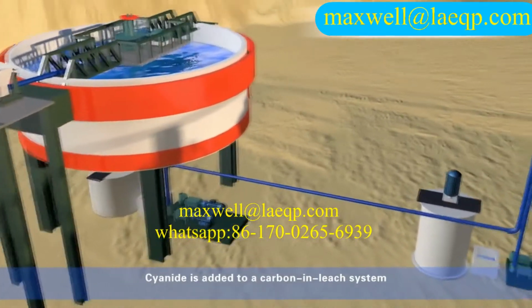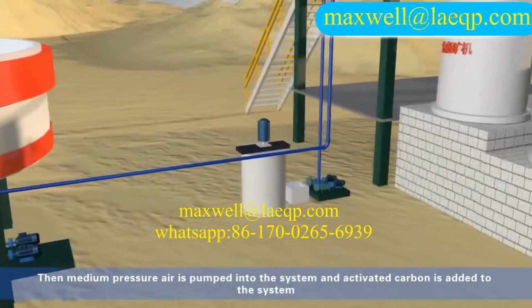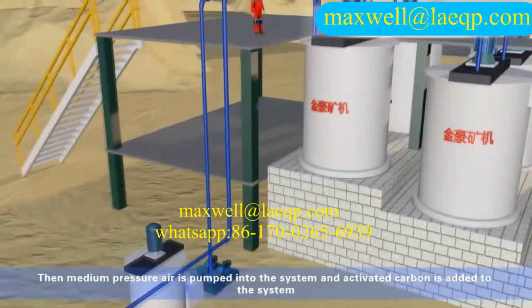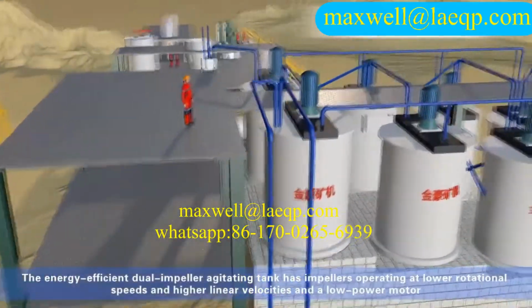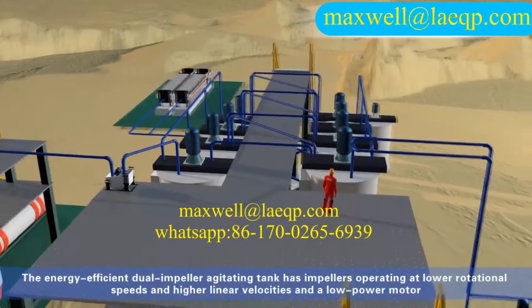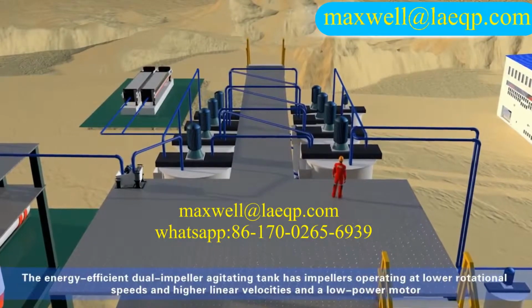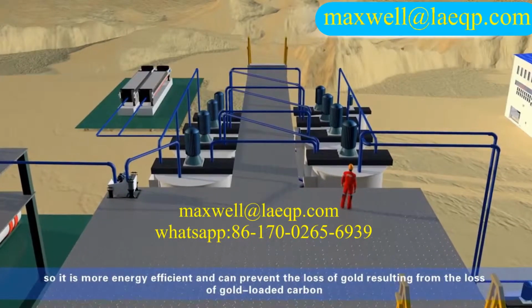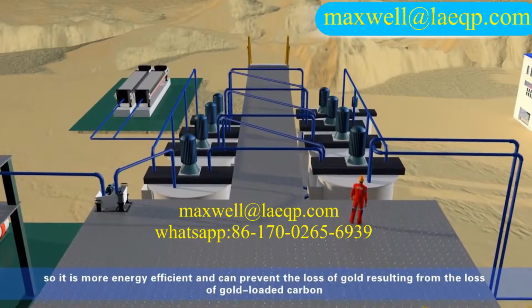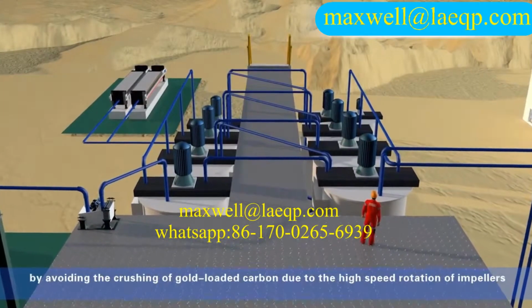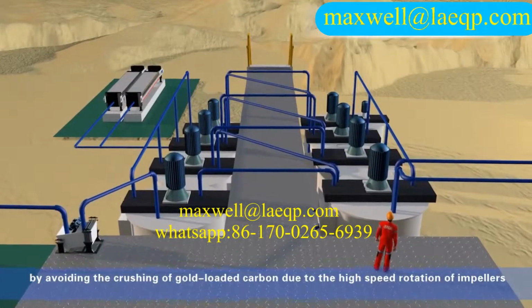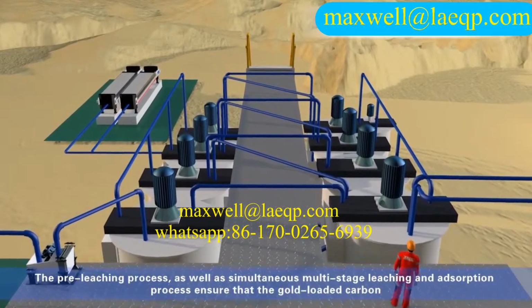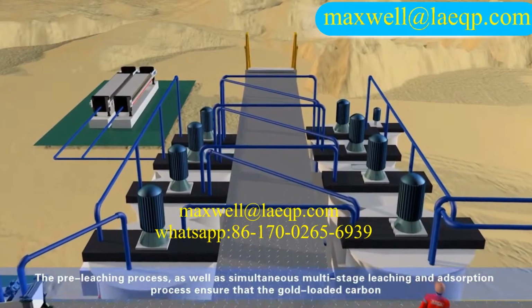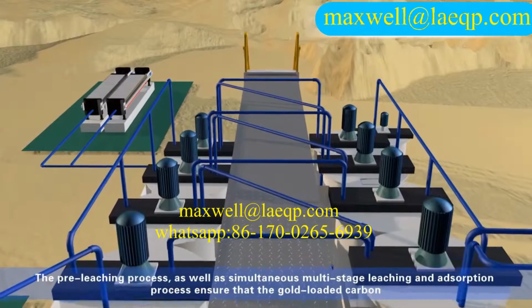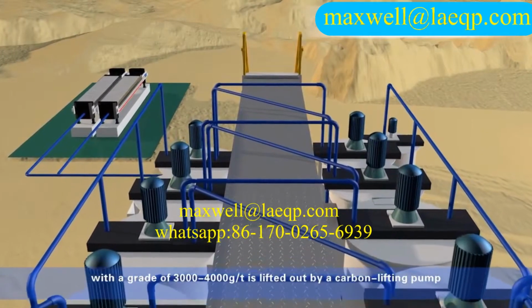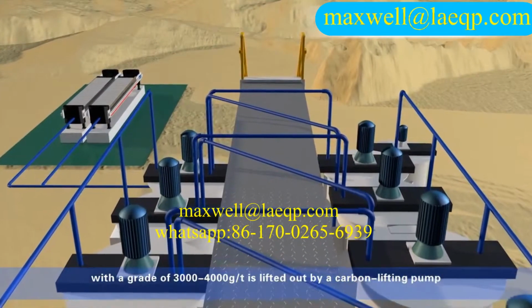Cyanide is added to a carbon-in-leach system. Then medium pressure air is pumped into the system. Activated carbon is added to the system. The energy-efficient dual-impeller agitating tank has impellers operating at lower rotational speeds and higher linear velocities and a low-power motor. So it is more energy-efficient and can prevent the loss of gold resulting from the loss of gold-loaded carbon by avoiding the crushing of gold-loaded carbon due to the high-speed rotation of impellers. The pre-leaching process, as well as simultaneous multi-stage leaching and adsorption process, ensure that the gold-loaded carbon with a grade of 3,000 to 4,000 grams per ton is lifted out by a carbon-lifting pump.